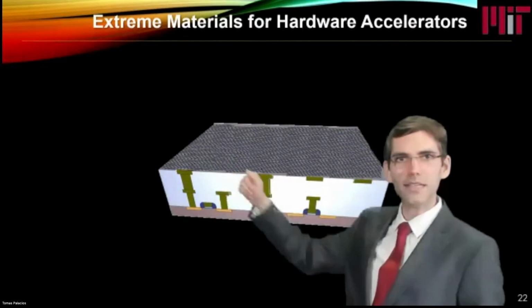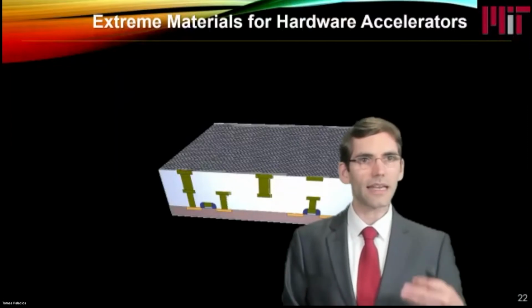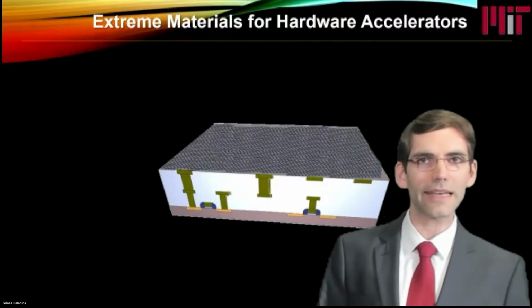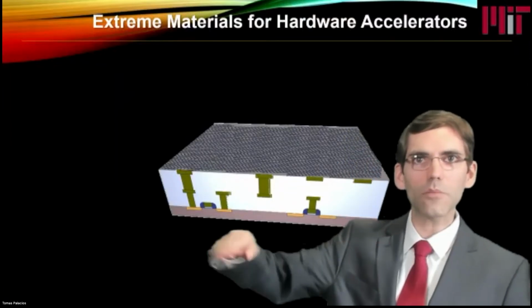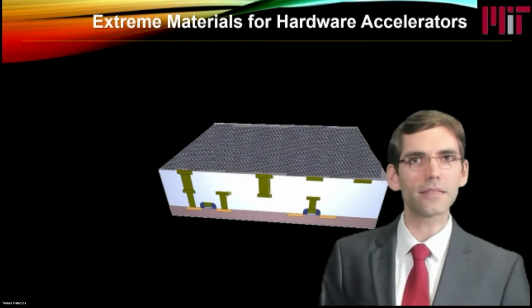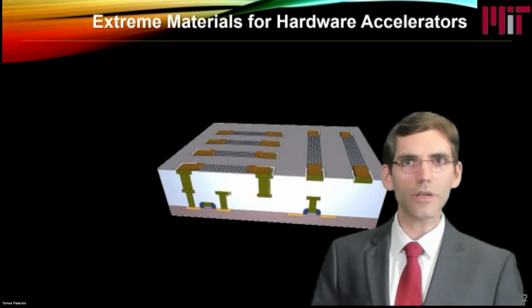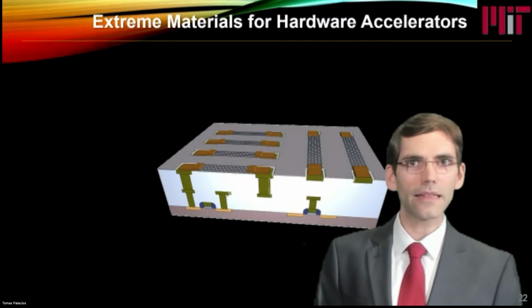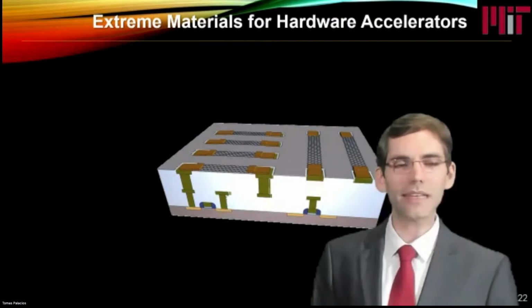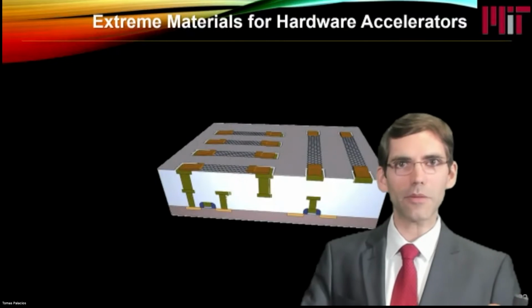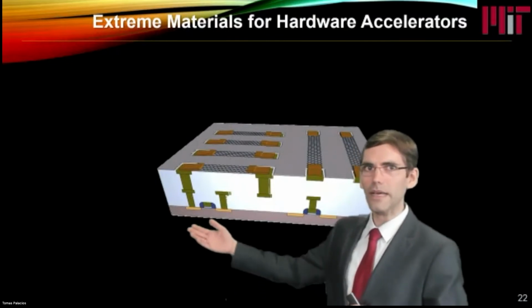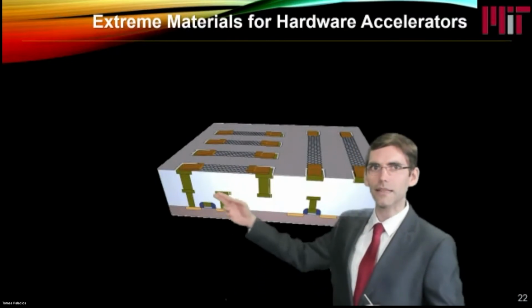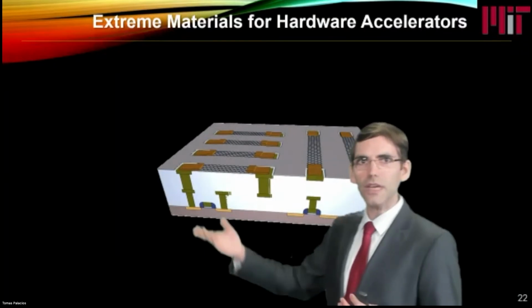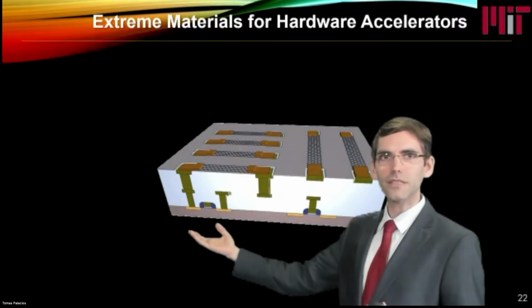deposit or synthesize these extreme new materials, like 2D materials, like graphene, on the very top of the fully fabricated silicon wafer. And then we pattern and fabricate the devices on these new materials using a thermal budget that doesn't degrade the silicon devices underneath. And in that way, we can bring new functionality to the silicon chip.